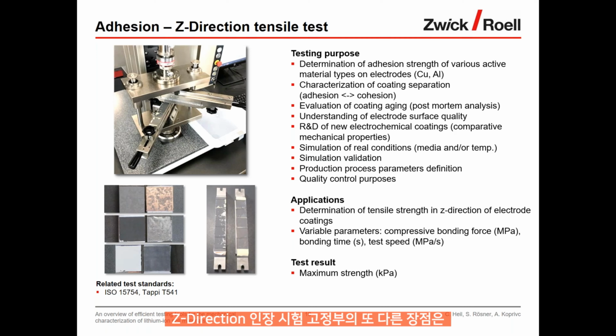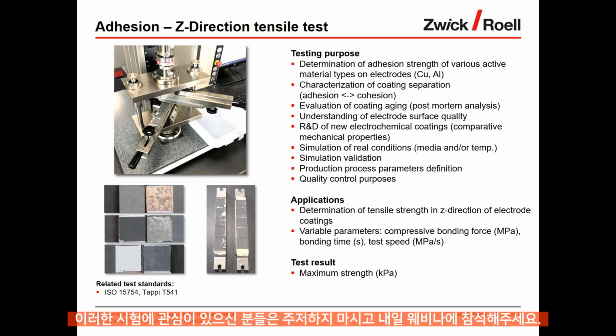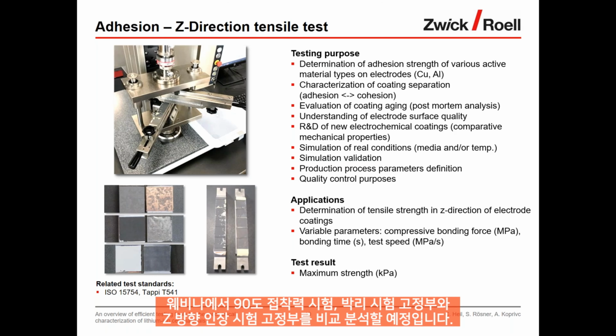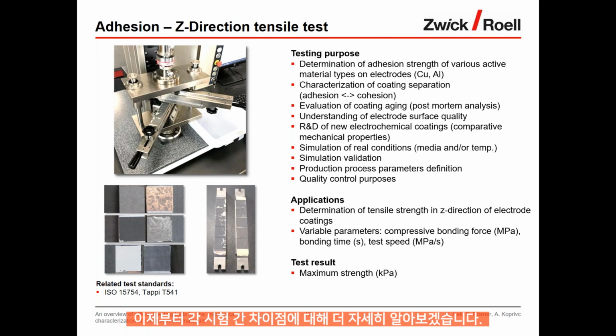One other good feature of this fixture is that it offers you 5 statistically useful tests with only a one-time sample preparation. So it really is a very efficient tool for this kind of test. If you're interested in this test in more detail, then please do not hesitate to join us for tomorrow's webinar, where we will compare the 90-degree peel test fixtures and the Z-direction tensile test fixture. We'll go into more detail about the differences of those two tests.